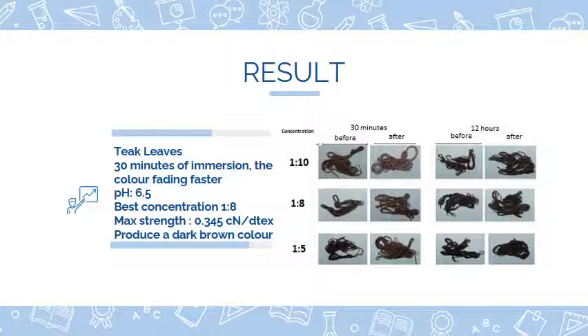In this study, teak leaves produce a dark brown color. This pigment arises due to the presence of anthocyanin content in teak leaves. From the image, we can see in 30 minutes of immersion, it is shown that the teak leaves produce a mellow brown color for concentration 1/10 before fixation and mellow brown color after fixation. At concentrations of 1/8 and 1/5, the pigment was dark brown before fixation and mellow brown after fixation.